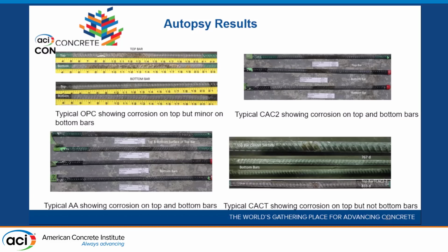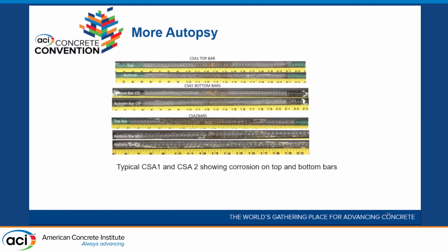And the CAC2, with a much longer time than everything else on here, because they were the very last things to fail. They had a little bit of corrosion on the top, CAC-T on the top bar, and very little on the bottom bar. So the basic OPC and the typical OPC and CAC-T were the only ones that did not have corrosion on the bottom bars. There shouldn't be much chloride on the bottom bars.